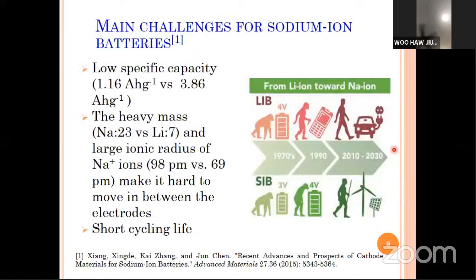There are some main challenges for sodium-ion battery. First of all, the low specific capacity compared to lithium-ion battery, 1.16 ampere-hour per gram compared to 3.86 ampere-hour per gram. And the heavy mass of sodium, which is 23 versus lithium 7, and the bulky size, with a large ionic radius of sodium ion being 98 picometer versus 69 picometer for lithium, makes it very hard to move in between the two electrodes, cathode and anode. And this also causes a short cycling life of the sodium-ion batteries.